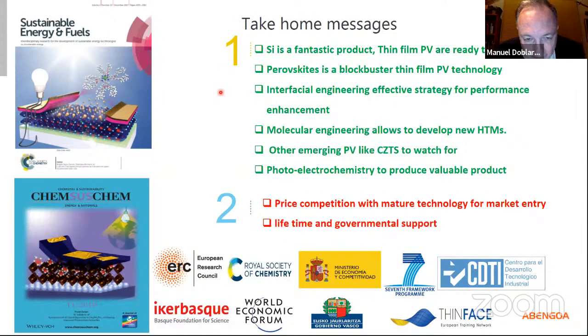Jose Angel Peña asks, what about the aging of these materials? He's talking about the loss of properties over a long time, not exactly stability, but about the aging. And I can read his next question. What about the use of perovskite in photoelectrolysis? Have you performed it? Aging, as I have commented, what we have observed with time is that the organic molecule evaporates and lead iodide remains, because we can see from the color that the black color became yellow, so it means only lead iodide is there, and then the devices will not work. So we are using different flavors I have given you today to increase the stability, like putting layered perovskite and putting a two-dimensional material, graphene or MoS2, on top of it to make it more stable.